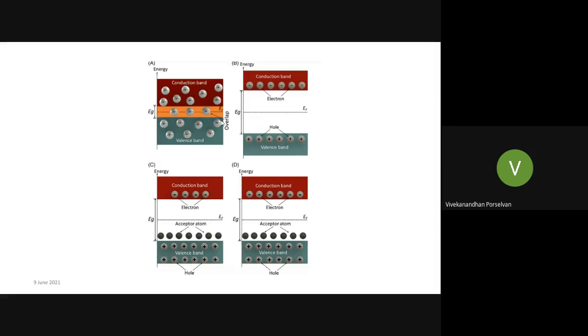Talking about the contrast in insulators, the band gap is very high, more than 3 electron volt. Thereby it has very low thermal conductivity and very low electrical conductivity. So which means that we have to tune it. In a semiconductor material with a band gap close to 1.75 to 2 electron volt, it can trade off between the electrical conductivity and the thermal conductivity.